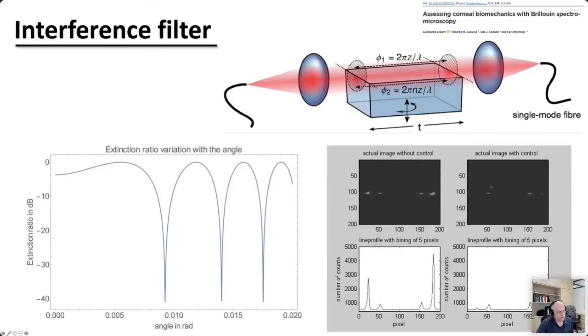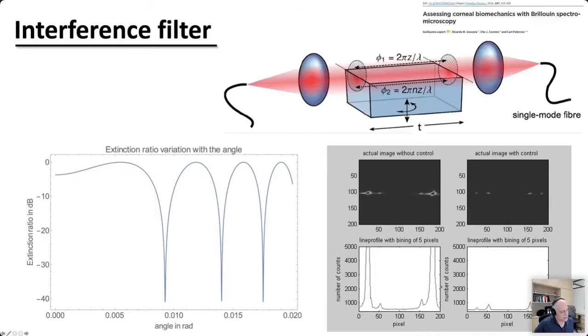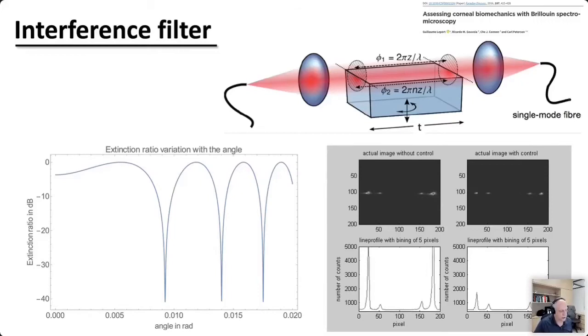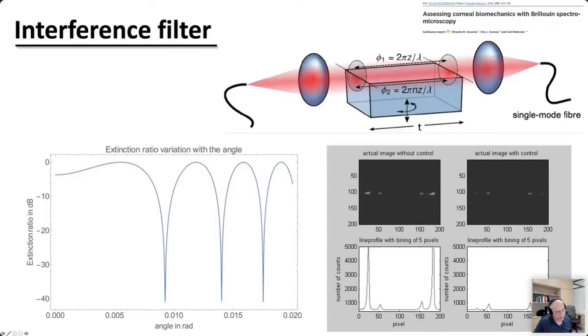This is basically how a Brillouin spectrum looks on the camera. We have a closed-loop control, and these peaks are the Brillouin peaks. Without control there is quite a lot of fluctuation due to interference — mostly from specular reflections in the system. But when we switch the loop on and extinguish these peaks, you see that it suppresses just the Rayleigh peak without affecting the Brillouin peak at all. This is very important; otherwise the Brillouin peak would be swamped by the Rayleigh light and we would not be able to see the spectrum.